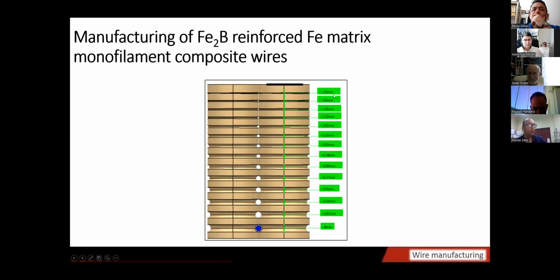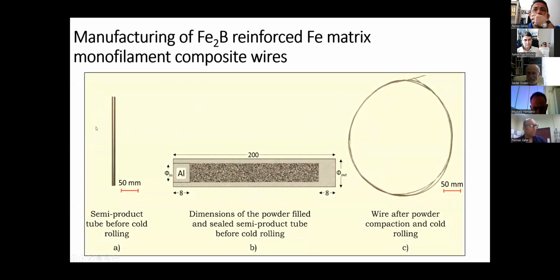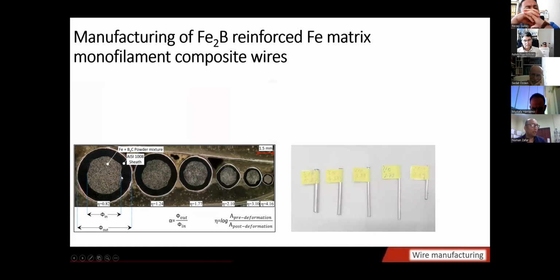After filling the tubes, they are subjected to this cold rolling device from 8 millimeter to about 1 millimeter. The cold rolled wires reach from this state to this state. These are the dimensions of the material, and they are capped with aluminum so that the powder does not come out whenever we subject them to cold rolling, plastic deformation. This is the cross section of the wires. At this state, we have only powder mixtures inside the core, and outside we have steel sheets. And as you go down, the deformation level increases, and these are the wires from the side view.